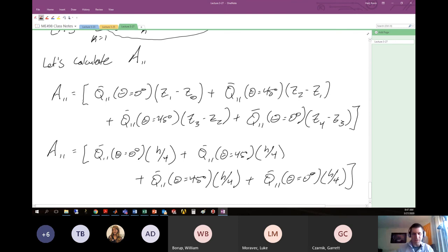All right, so now you see each one of the individual stiffnesses of each one of the individual layers, okay? Here we have the contribution from layer 1, layer 2, layer 3, layer 4. Each one of them is contributing a certain amount of stiffness when we pull on the laminate, how much it's resisting that pulling to give us a certain amount of strain. And the contribution of each one of these is sort of magnified by the value H on 4, right? So each one of them has a weight of H on 4.